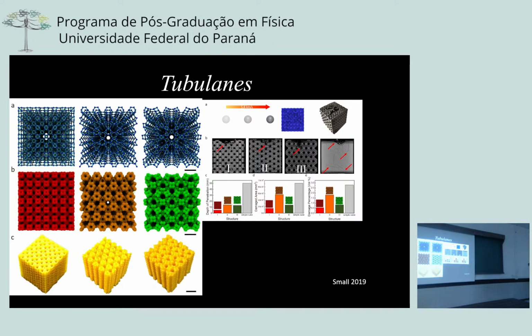We made a tubulane structure. This is where Cristiano made the structures at an atomic scale. We may print them at macro scale. And by printing this topologically complex structure, we can have an impact-resistant 3D printed structure as well. When we talk about plastic, we assume it's soft and weak. But if you engineer the topology, you can have a porous structure with impact resistance almost like metals. Apart from that, it has a lot of interesting aspects as well.